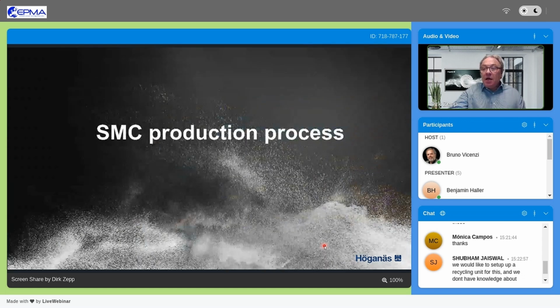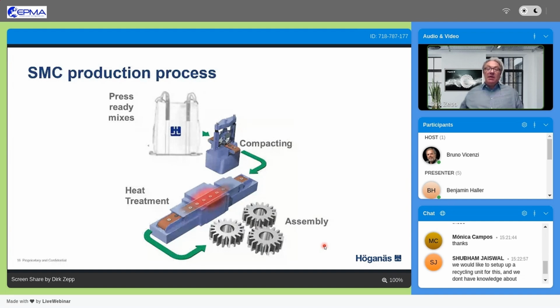The production process of SMC material, as I mentioned earlier already, is that normally the SMC material is supplied in big packs of 1 ton of material. Then our direct customers use this material for the compaction and afterwards for the heat treatment. The components that come out of the heat treatment, after a quality check, of course, should then be assembly ready. And that is quite an important message, that we still need to educate nearly all the designers of companies that are designing components with this material, that these parts that come out of the heat treatment should not be machined. There should be no additional operation.